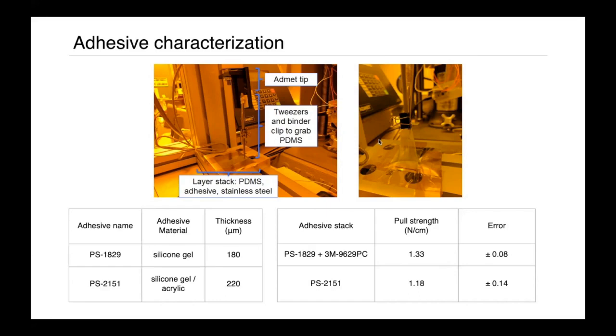What we found from the pull strength test is that a combined adhesive stack of silicone gel plus a 3M double-sided acrylic tape was the combination with the highest pull strength of 1.33 newtons per centimeter, whereas the double-sided silicone gel and acrylic polymer science tape had a pull strength of 1.18 newtons per centimeter.